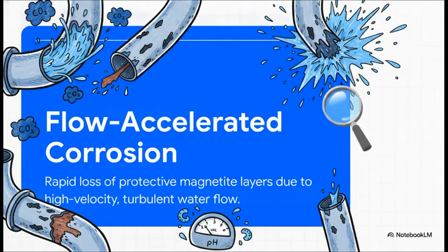See, your carbon and low alloy steel pipes naturally form a protective metal oxide layer called magnetite. But when you have areas of high-velocity, turbulent water or two-phase fluid flow, that protective armor is literally stripped away. And remember those carbonates and CO2 we talked about earlier? Well, by lowering the pH of the water, they make the environment so much more aggressive, supercharging the FAC process until the pipe wall simply thins right out and bursts.